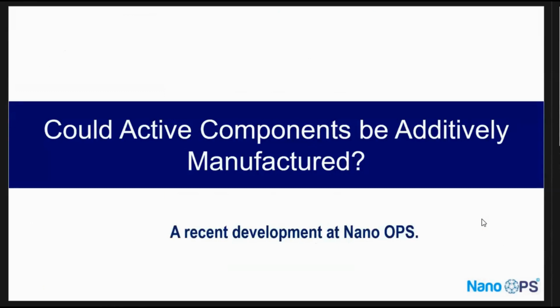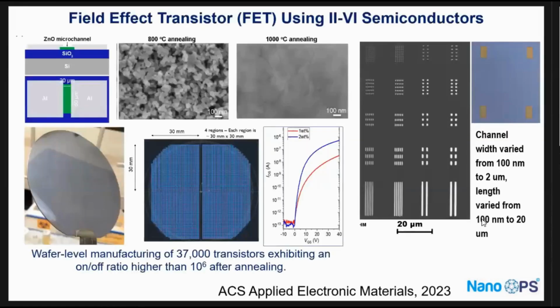Okay, so now we looked at the capacitors. What about printed semiconductors and transistors? This is a recent development. We started with something that's easy to obtain. By the way, if you want to print III-V semiconductors, it's very hard to get nanoparticles. You have to make your own nanoparticles, for example indium phosphide, which we did. And to get GaN particles, you get large GaN particles, because they prepare them by taking GaN wafers and grinding them, going through ball milling and so forth. So zinc oxide was easy to get source wise, but it needed annealing at high temperature. In this picture, you can see these particles are about 50 to 100 nanometers. At 800 C they're still particles. When you go to 1000 C, you can get a solid film.